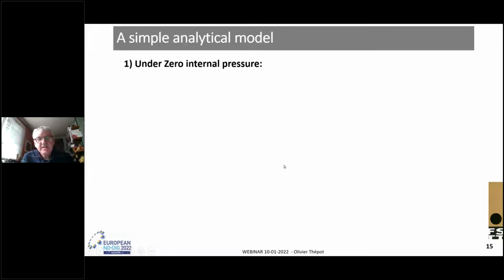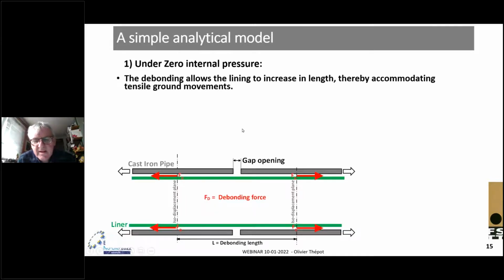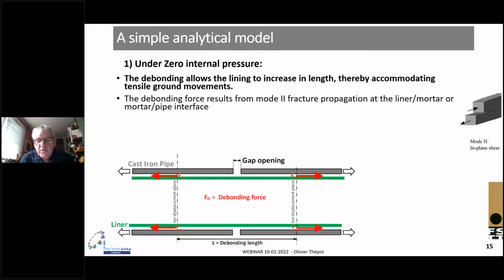The analysis of the result can be done with a very simple model. The key concept is a debonding length. Indeed, the liner must debond from the cast iron pipe to accommodate imposed elongation. The debonding force results from mode 2 fracture propagation at the liner-mortar or mortar-pipe interface.